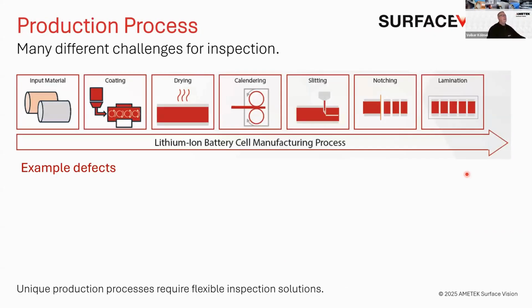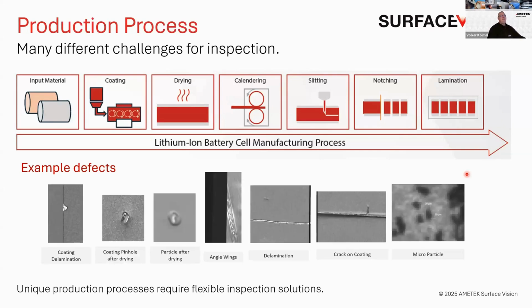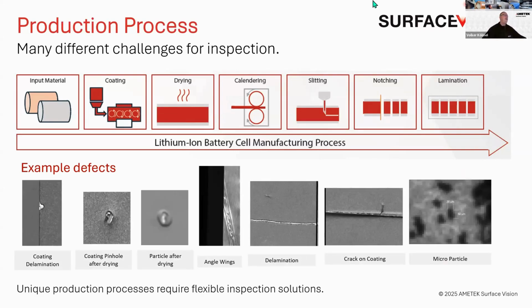Let's talk a little bit more about the different areas along the process. So we will have different tasks along the process, and you can imagine on each of the process steps, like coating, where you apply the slurry on the collectors, or on the drying, when you remove the solvent, and then the calendering, where you then compress the density, uniformity, and then later you have the slitting because you cut this in slits. So you prepare this later for the cell assembly, and then the notching, you separate this, or you have the singulation where you have then the individual pieces of the half cells or of the electrodes before it goes further in the stacking process. So each of them has a different challenge.